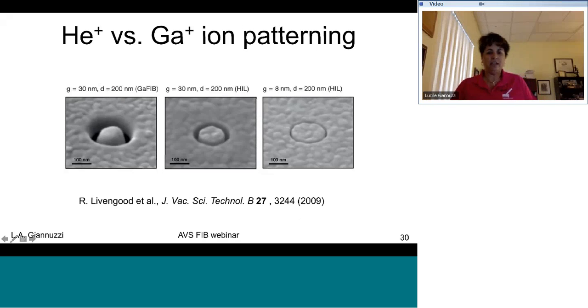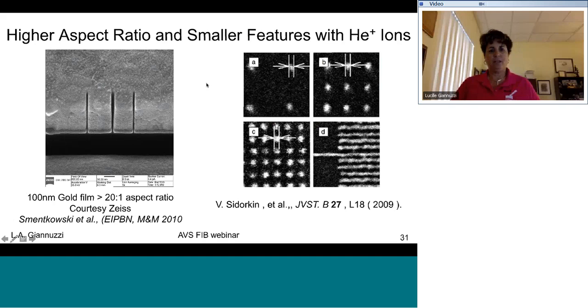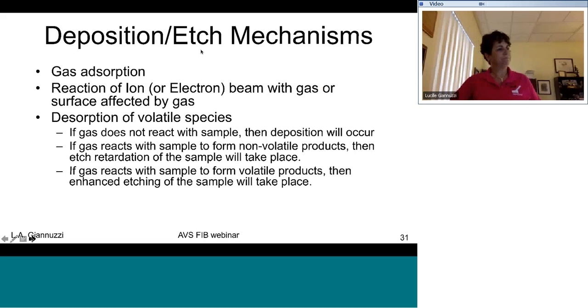Okay? And this is emphasized again in this work by Livengood and co-authors at Intel, as well as Zeiss. So this is a gallium FIB. This is a helium ion microscope. You can see that you've got much better defined features using the smaller mass helium ion compared to the larger gallium ion. Not only that, you can get higher aspect ratio features with helium on this edge of the surface. In addition, you can also just use the helium for, not necessarily etching, but photolithography type applications. Okay.